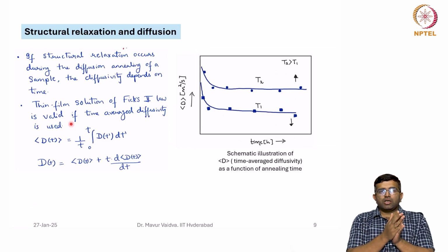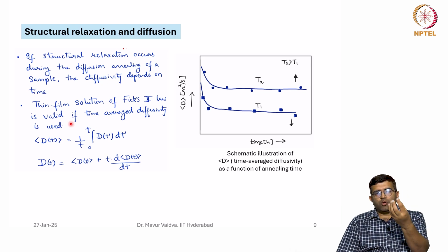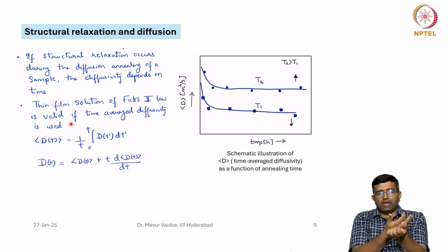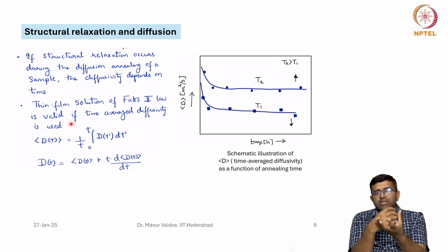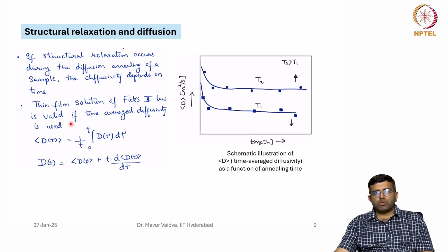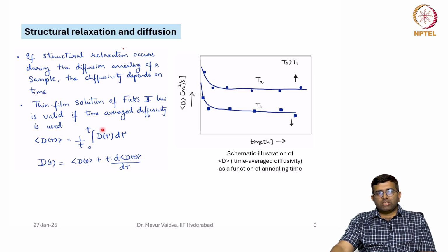If structural relaxation occurs during the diffusion annealing, so suppose you take a glass and you deposit a tracer and you want to study the diffusivity in that glass, but during the annealing the glass undergoes structural relaxation, then the diffusivity will depend upon time. So if for such a radiotracer experiment we still want to use the thin film solution of Fick's second law, then we have to use a time averaged diffusivity. The time averaged diffusivity D_avg is written as 1/t times the integral from 0 to t of D(t') dt'. Here t' is the time, and D(t), the instantaneous diffusivity at any time, can be written as the average diffusivity plus t times dD/dt.